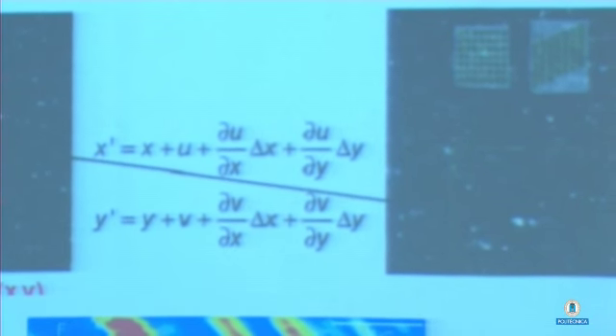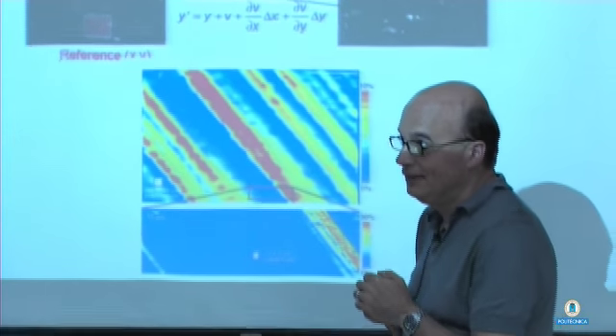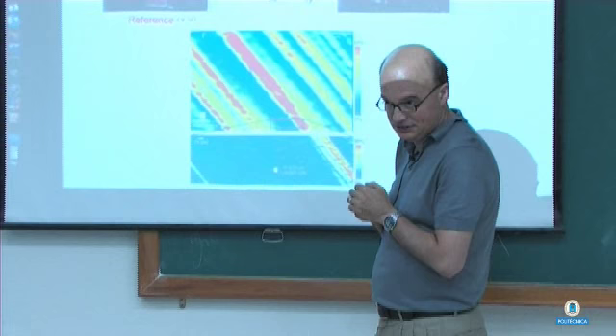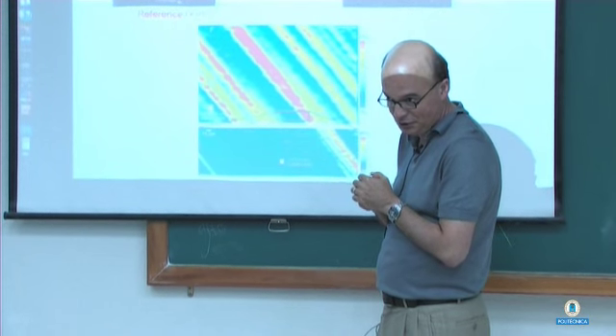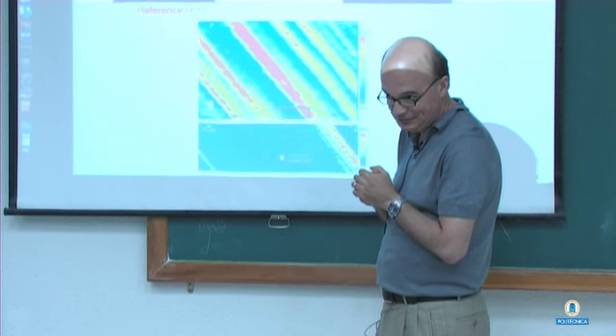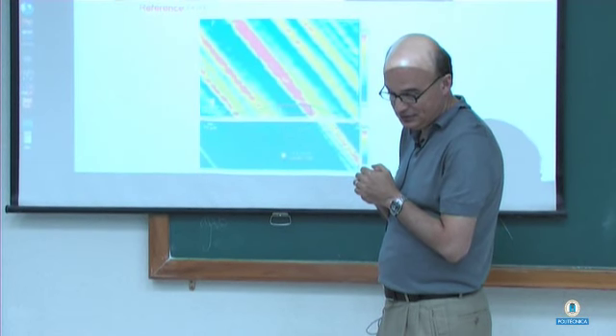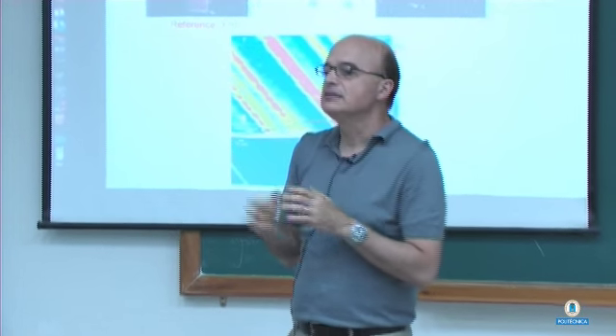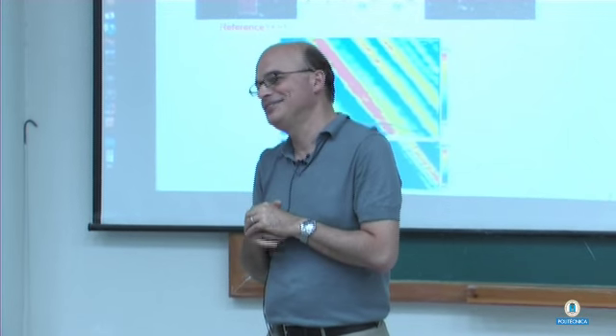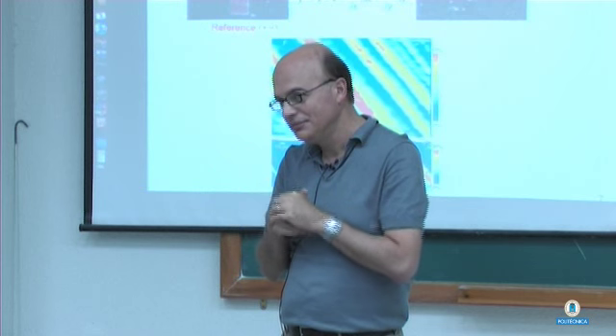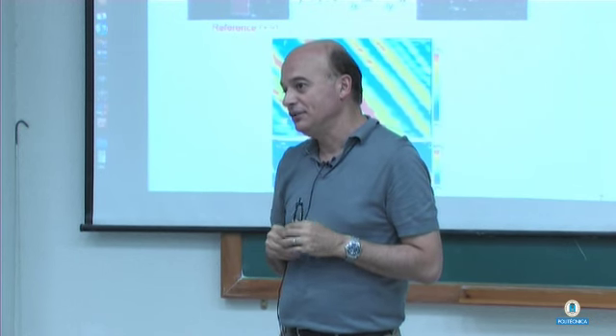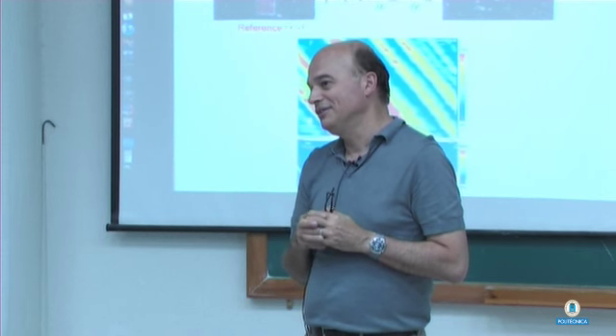The ones used here are very fine. And how big are the speckles? Is that what you're asking? I think they are sub-microns, 0.03 microns, something like that. It's very small. And you deposit this speckle? We are doing it different ways. One is using actually an airbrush, you know, just like in a, yeah. We are using it at high temperature, so we are using high temperature paint with small particles in it, things like that. So we're playing with a lot of things.